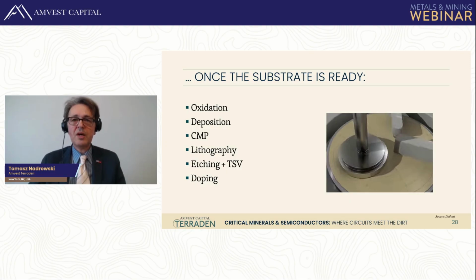Okay, so once we have a substrate ready, let's say the substrate is a silicon substrate. The first thing that will happen once you have generated that wafer, it actually has to undergo a process called epitaxy. So in this case, silicon gases are heated, and atoms of silicon are again deployed on top of the wafer to align with the existing crystalline structure. It makes it a very pure, very smooth product, which is then oxidized for insulation.